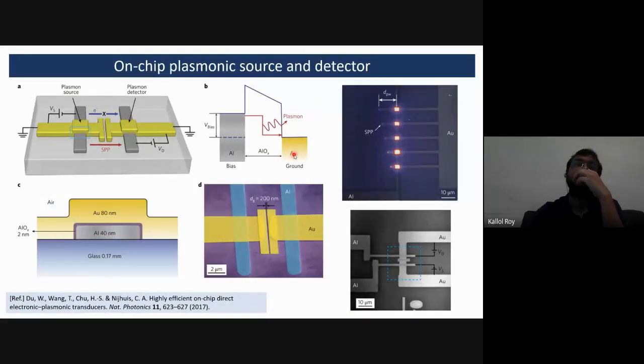And this is one typical example where you can see that it's a gold electrode and then an aluminum electrode, which are separated only by 2 nanometers, and then inelastic tunneling happens, and that excites plasmons. And then similar phenomena can also help in detecting the plasmon. So on one side you have a plasmon source, on the other side you have a plasmon detector. The advantage of this is that this is happening via tunneling, and hence it can operate at very high speed.